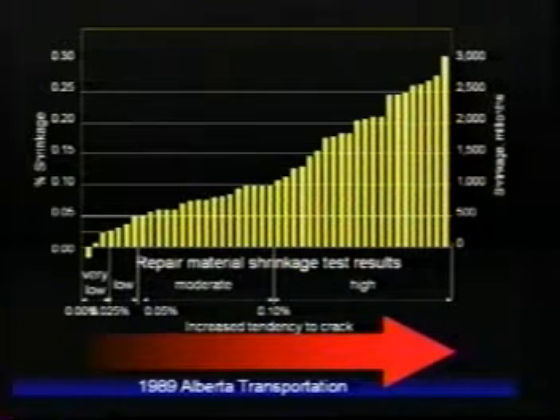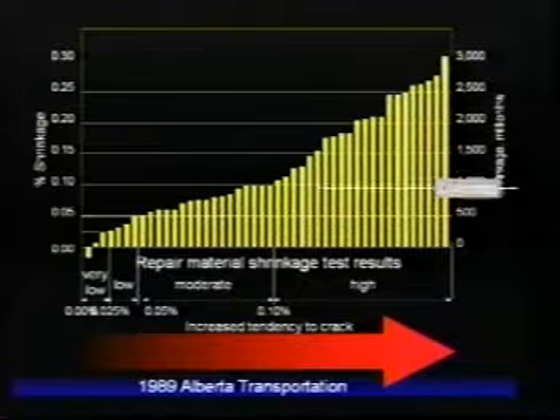And generally there's a correlation between less shrinkage and less cracking that will take place. So it's believed that shrinkage below 0.05% in accordance with C157 is the recommended material. You can see that many materials do not meet this requirement, and it's a critical aspect. Just in relation to this particular chart, ready-mix concrete is about 0.05%.